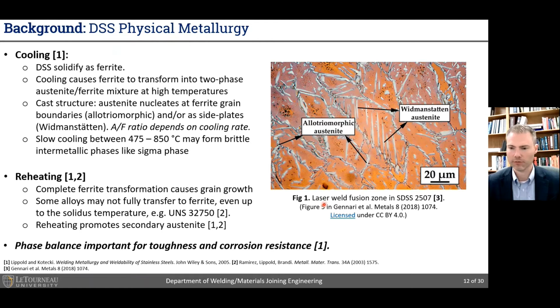From a laser weld fusion zone, and depending upon the cooling rates, if we have fast cooling rates, we will tend to suppress the nucleation and growth of austenite and will result in a ferrite-rich microstructure, such as one sees here. In this case, the austenite etches light.